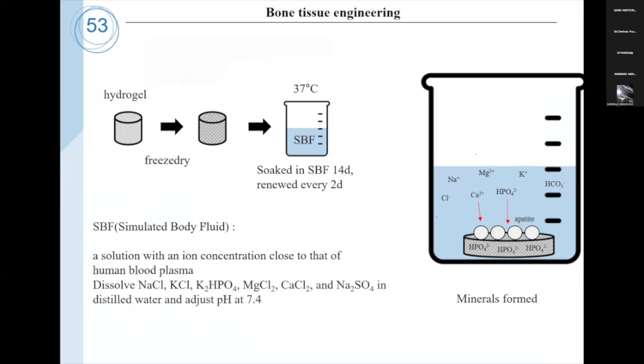So once we prepare any scaffold, hydrogel, or polymer scaffold with a porous structure, then we soak it in SBF solution, simulated body fluid solution, at 37 degrees centigrade, human body temperature. Then any scaffold or hydrogel starts to biomineralize. It means hydroxyapatite can be formed on the surface or within the scaffold under a particular time, because the SBF solution is very close to the human blood plasma.